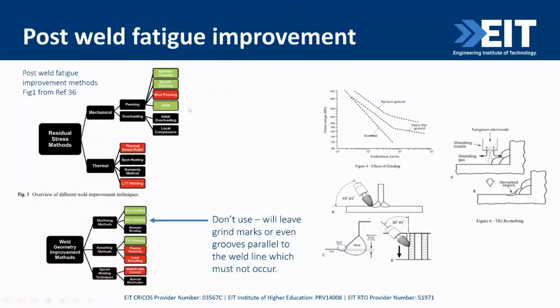Okay, the post-weld fatigue improvements we talked about. Good summary there. I'll leave it with you. The residual stress, your peening and high frequency mechanical impacting, etc. For thermal, you're thermally stress relieving. For weld geometry methods, your machining or your TIG remelting or whatever, please don't use disc grinding.